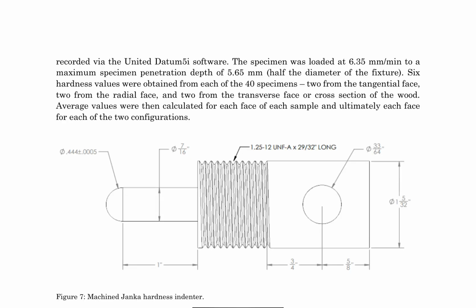The experiment measures the Janka hardness of wood specimens using a custom-built fixture and United Datum 5i software. Specimens are loaded at 6.35 mm per minute to a maximum penetration depth of 5.65 mm, which is half the diameter of the fixture. For each of the 40 specimens, 6 hardness values are obtained from 3 orthogonal faces: 2 from the tangential face, 2 from the radial face, and 2 from the transverse face or cross-section of the wood. Average values are calculated for each face of each sample and ultimately for each face of the 2 configurations.